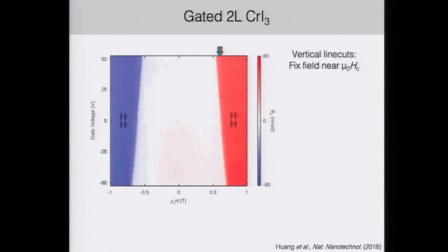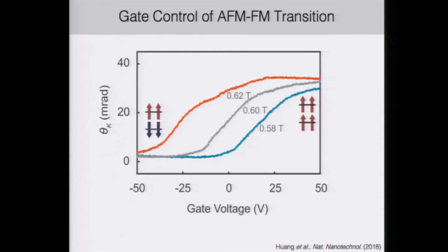Here we're going to fix the field near the transition and then only change the gate voltage. When we do so, we're able to achieve gate control of the AFM-FM transition in bilayer chromium iodide. So here at different fixed magnetic fields, just by sweeping the gate voltage, we can go from a 0 Kerr rotation up to a finite value and back and forth.